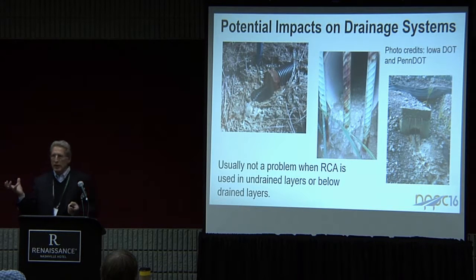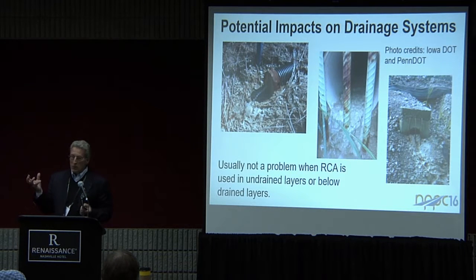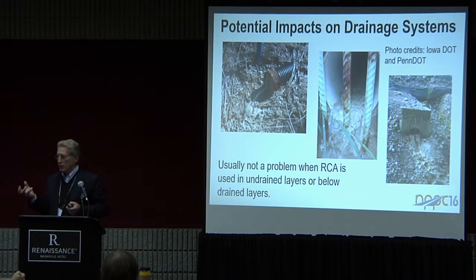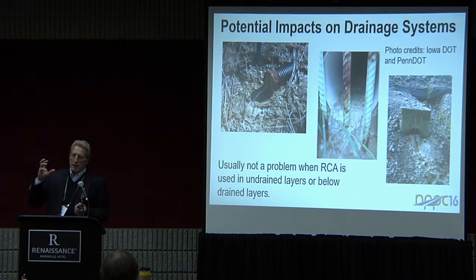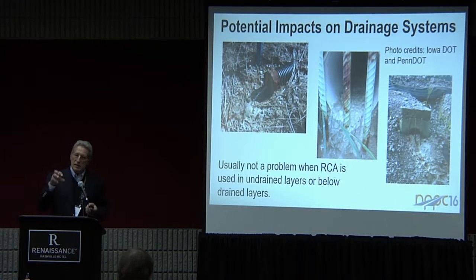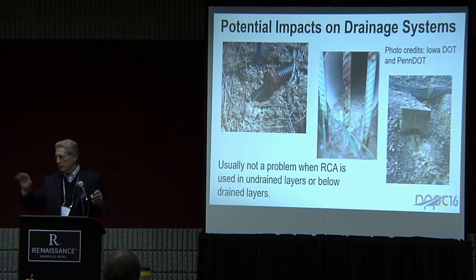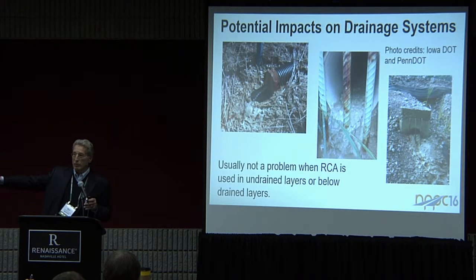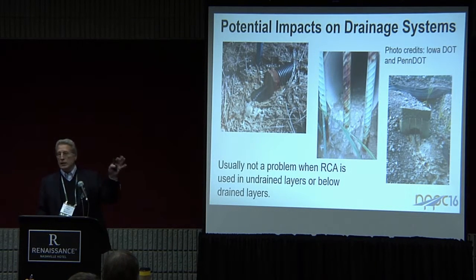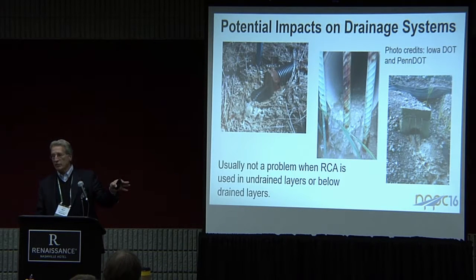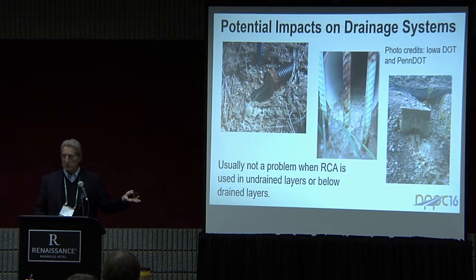What we have happening here is that, along with having possibly unhydrated cement grains, we have a lot of dust that's produced in the crushing operation. And in addition to the dust, which we'll call insoluble residue, we may also have calcium hydroxide present in the cement itself. Okay, and calcium hydroxide is very soluble in the presence of water. So if you run water through that and you leach that calcium hydroxide out, it goes into solution. Calcium ions go here, hydroxyl ions go there. Hydroxyl ions contribute to a relatively high pH value that you get. And the calcium ions will combine later on with atmospheric carbon dioxide, and you get calcium carbonate, limestone, essentially precipitating out.